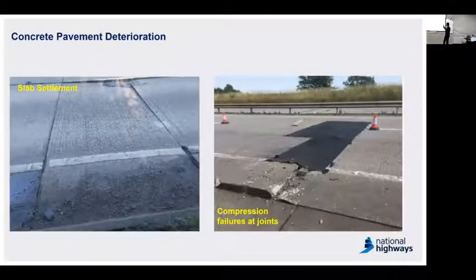Basically, these sorts of defects are likely to be on jointed pavements, particularly in hot weather conditions, when the concrete tries to expand due to defective joints, if it's a locked joint or there is not enough room for the concrete to expand. What tends to happen is it comes up as a blow-up, an inverted V. So this is actually a safety critical defect. The repair we are looking at is sometimes done with asphalt, mainly for emergency reasons, but that's not the proper repair. So it has to be followed up with a treatment option.